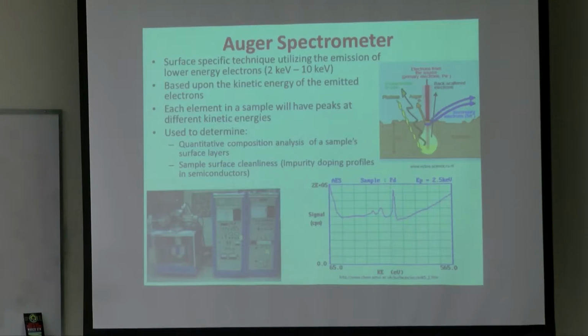And so the idea behind this spectrometer is based upon the kinetic energy of the emitted electrons. So how fast these are going to be traveling, or how much energy they have. Different kinetic energy will result from different types of samples. So different elements will give you different types of structures. So you're able to determine what's inside of a sample based upon knowing the kinetic energy of the material. So this is used to determine quantitative composition analysis of the surface layer of a sample and how clean your sample is. So if you're looking at a semiconductor and you want to look at the impurities when you're doping the semiconductor, this is what's utilized for that.